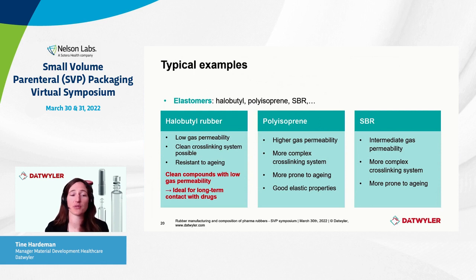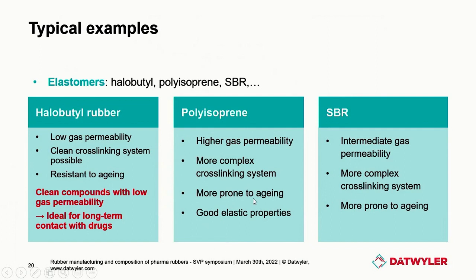So as you can see, these properties make it possible to get a clean compound with a low gas permeability using halobutyl rubber, which is why it's so popular and why it's also ideal for long-term contact with drugs. If you compare this, for example, with polyisoprene, you will see that this one has a much higher gas permeability, and it also has a more complex cross-linking system, meaning that it's more difficult to get a clean chemistry there. So you need to add some accelerators, etc., to get this cross-linking going, or you need to shift to other types of cross-linking systems.